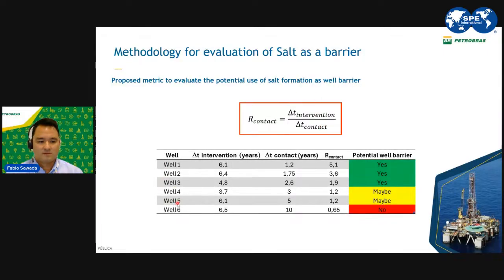We did this for 6 wells where we have similar intervention times, like 6 years, 4, 3, and we modeled the salt, and we saw how much time the salt would take to touch the outer diameter of the casing, and the parameter is shown here. So we could define a range, so we can have a high probability of the well barrier being formed in the salt section, or not. This is something that an operator could do in order to decide on running a bond log to see if the expected behavior of salt really happened in the field.